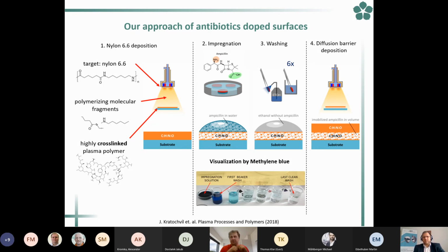That was tested for some different bacteria, and it was quite effective. But once again, that's the motivation why we combine it with these nanoparticles, because there we observed antibacterial effects for a longer time. So the motivation is to have the first shock from the antibiotics released from the nylon, followed by the release of ions of silver or copper. Yeah. Thank you very much.